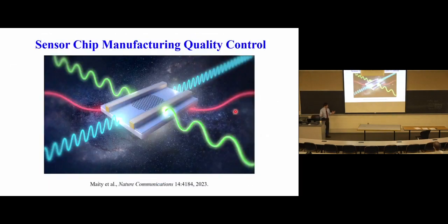So some of the recent results, for example, we really try to be able to control the manufacturing process. In fact, this is research towards screening high quality devices versus poor quality devices based on just their electronic properties alone. It's not sufficient. Basically, if we look at their on-off current ratio or their resistance, it's not enough. They may be very close to each other, but their sensing performance may be very different. It turns out the quality of that aluminum oxide passivation can be very important. If you have some pores or porosities in it, it will modify your sensing performance, especially in the water environment.